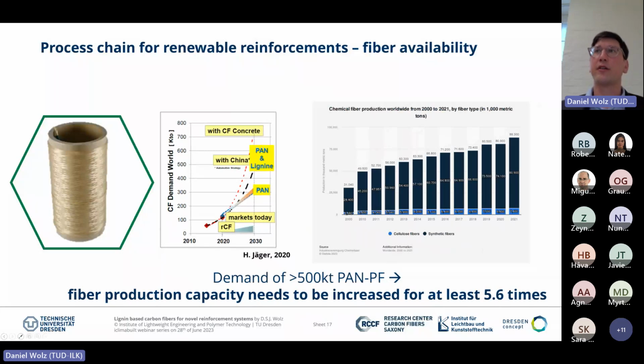The thing is, if you look at today's production of synthetic and cellulose fibers on the right side here, then you see that we have about 90,000 tons of production. There are two things. Not every polyacrylonitrile is included in there because this is made internally, but we actually would have to increase the capacity by at least 5.6 times. Meaning that we would have to increase the polyacrylonitrile production in the chemical industry by 5.6 times, meaning that we would have a need of 5.6 times of oil. This can't be the solution for renewable and ecological cities.